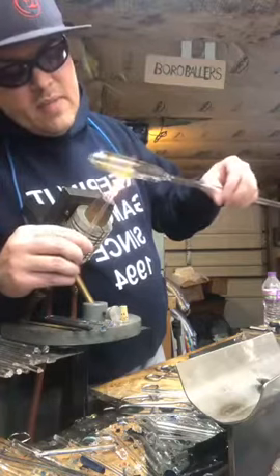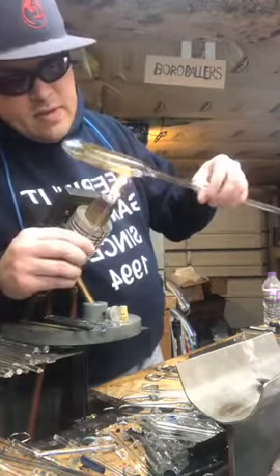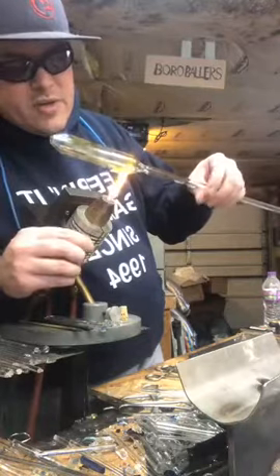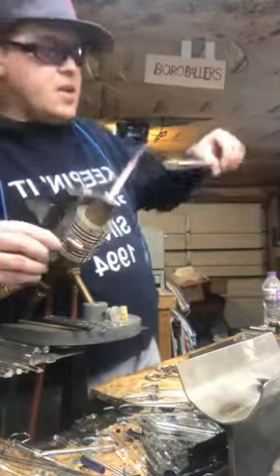And it sprays maybe a micron or two, I'm not quite sure. Nice real thin layer on the glass. At this point, I could take a scouring pad or a razor blade and scratch a bunch of this off. It's on the surface, but it's not truly bonded yet.